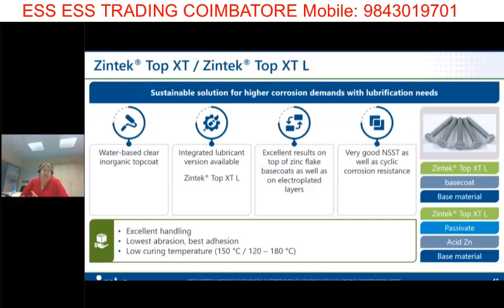But first, some other benefits of this process. It's really easy in handling. It has quite low abrasion, a very good adhesion, and for a top coat, also a quite low curing temperature of about 150 degrees with a range of 120 to 180.